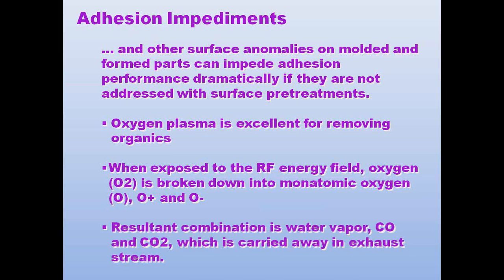When air plasmas generate the type of discharge we're looking for, we get a byproduct, and this is common also with plain plasmas and variable chemistry plasmas, of water vapor, small amounts of parts per million of water vapor, CO and CO2, very small parts per million. With variable chemistry plasmas, we get most of the inert gases that are part of the process, but of course, because they're inert, they're not critical exhausts. But nonetheless, all of this is carried away. Much of it is very benign and typically do not require any type of destruction systems that will add to the cost of an investment in these technologies.